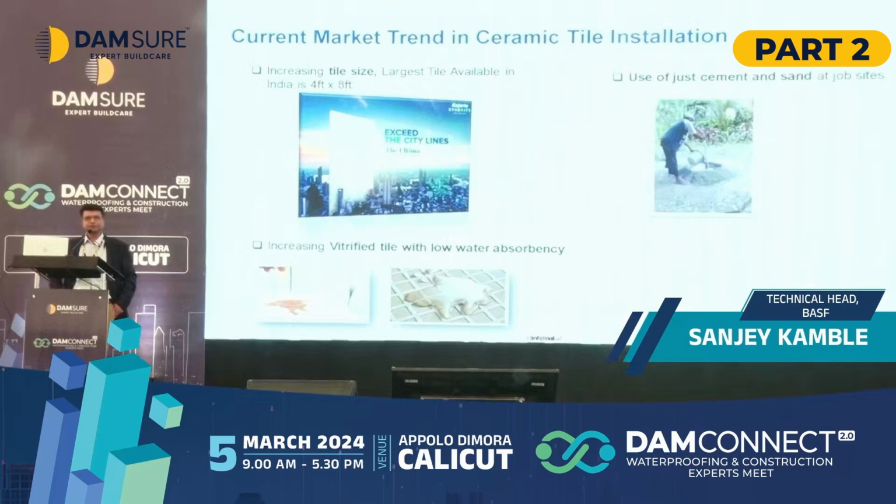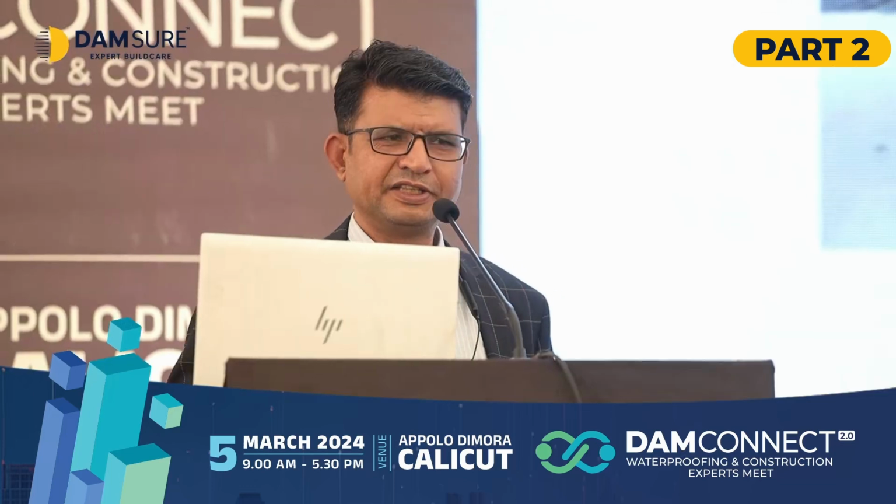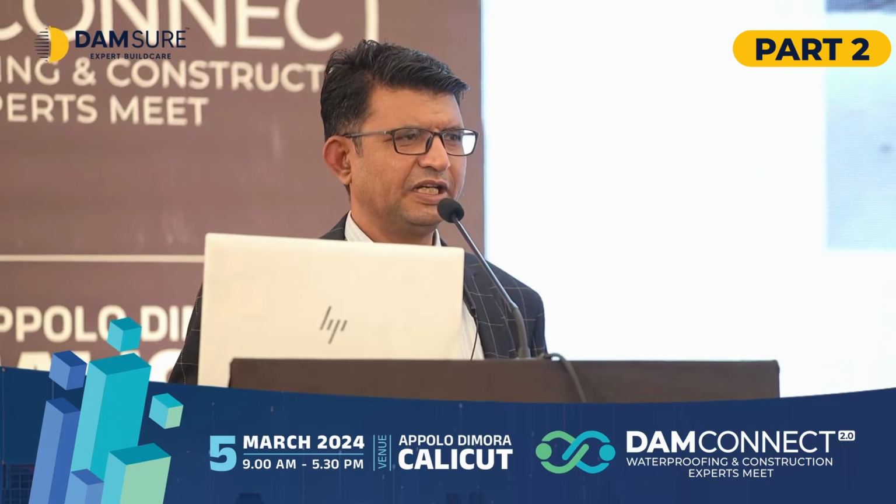And typically, most people just use cement and sand to fix these vitrified tiles as well. So ultimately what we see is an increase in tile failures. We could see the tiles getting debonded easily. So these are the thick bed and thin bed technologies which are typically available in the market.